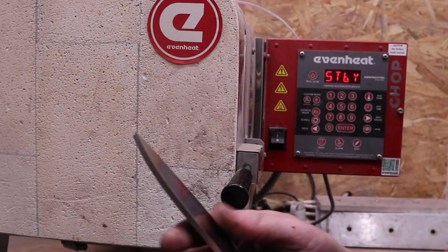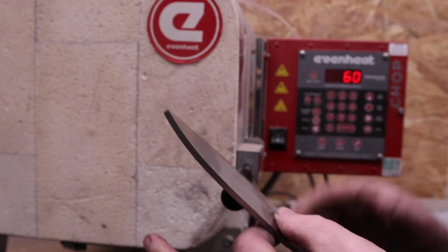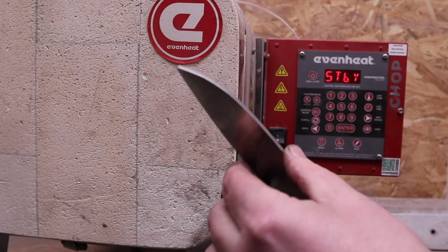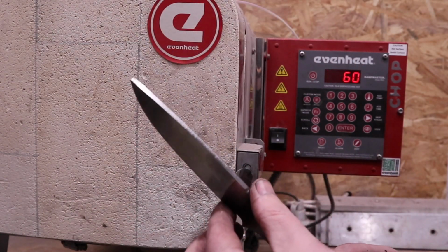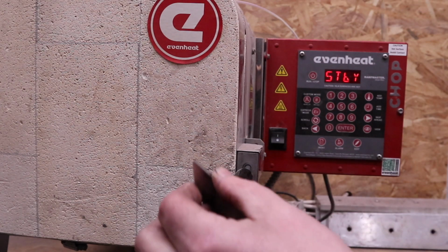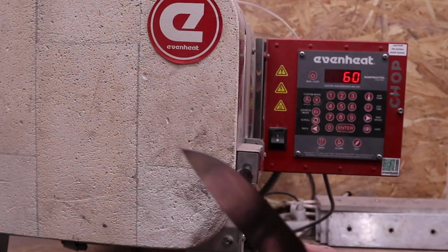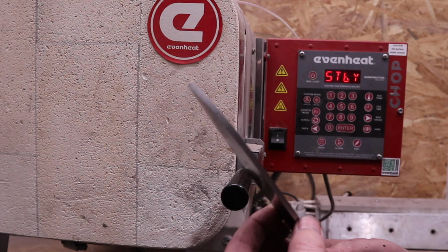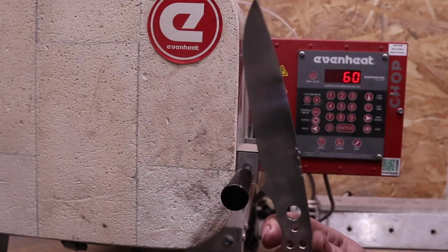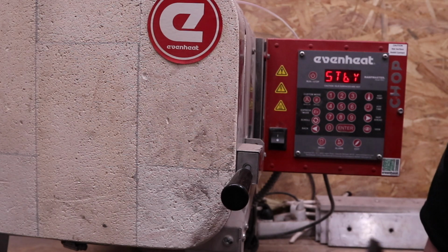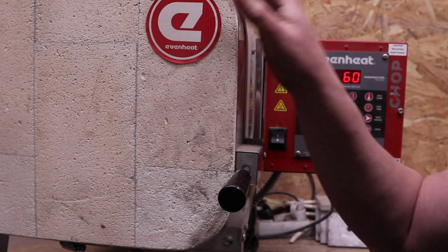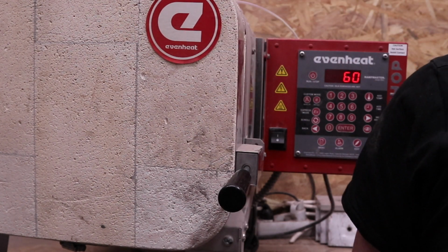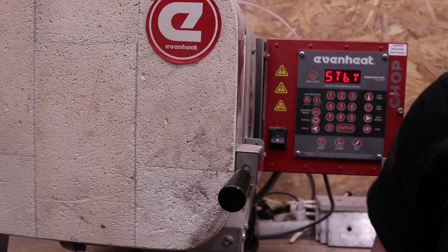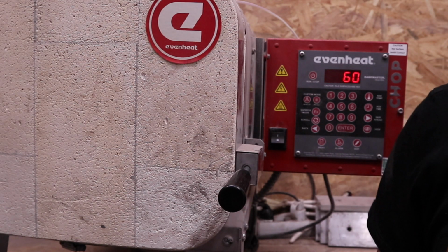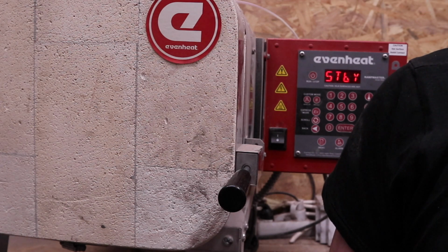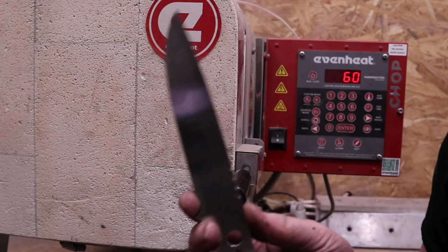Now, different types of steel are heated in different ways, such as to different temperatures, depending on, I suppose, the ingredients within the steel. Now, most steel manufacturers will generally publish the heat treating guidelines for their steel. And I've got a particular recipe which I use for O1, and that is to heat the oven up to 1200 degrees Fahrenheit, which is around about 610 degrees Celsius, or 640 degrees Celsius. I then add the steel for 20 minutes.